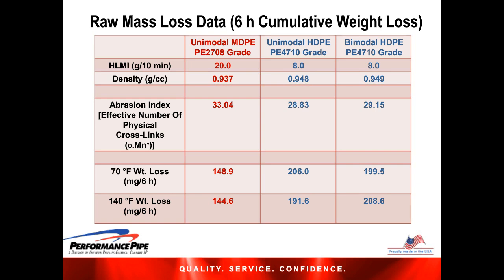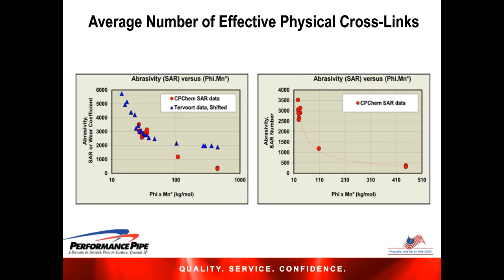One last slide on this, where we took the data that was published in the article that I referenced by Tervoort et al. That's the data in blue. And then Chevron Phillips had data for a number of different polyethylene resins that we had tested over time using the slurry abrasion response test, the ASTM G75, and that data on the left slide is superimposed with a shifted factor just to accommodate the data all on one slide in red.